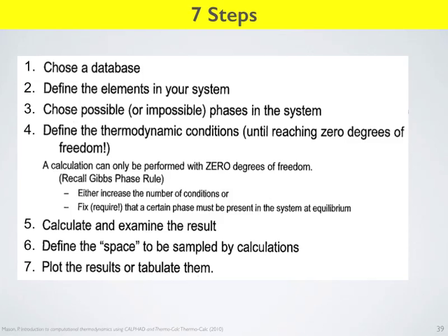You may have to use some of your materials science intuition to do this. So you go to the phase database and say, eliminate graphite. I think in the project we will do this. You will run a steels calculation with and without graphite. When you have graphite in, you will get this crazy phase diagram that looks like nothing you've ever seen in a textbook. You'll take graphite out and you'll get the textbook phase diagram. The reason being, graphite really is the stable phase on the timescale of millennia. Humans are not interested in that.